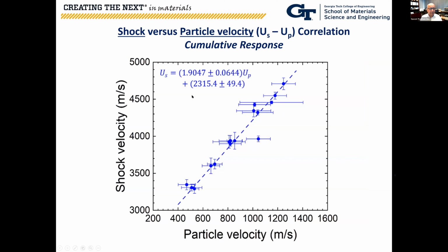If I then plot all of the data, this is all 19 experiments, plotting shock velocity as a function of particle velocity. In a way, we are not seeing much of a difference in the trend that has been observed, considering the error bars, which are fairly still large. There's no obvious trend one way or the other that we can convey here. At least it's indicating the material is not going through any physical or chemical change that would alter the density of the material.